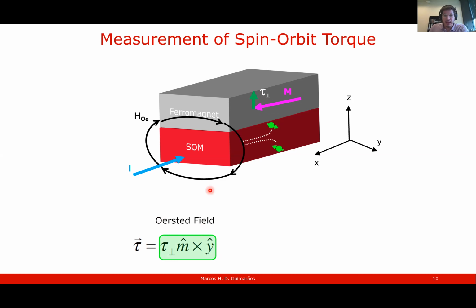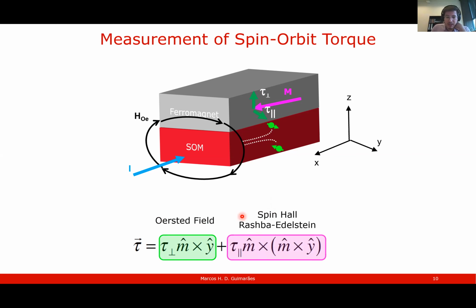Now, if we have, for example, spin Hall effect, the spins will be entering, pointing in the plane because of conservation of angular momentum. This wants to displace the magnetization in the plane, which causes an in-plane torque. And here we can write down the torque as a constant, so this tau parallel, an M cross Y, and Y here is the direction of the spin. And this torque is even in a magnetization direction.